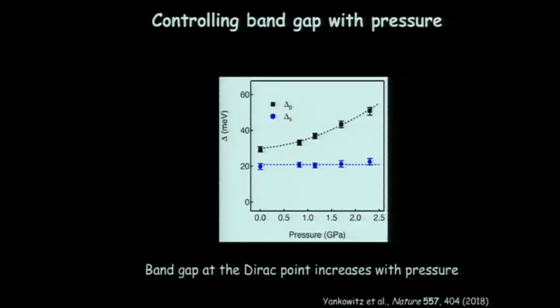So it seems like your picture has this out-of-plane modulation in the graphene lattice. Yes. So is that coming from your measurement, or can you prove that out-of-plane modulation scale in your measurement somehow? Yeah, so unfortunately with the STM, you don't really get true topography information because there's always the integral of the density of states on there.